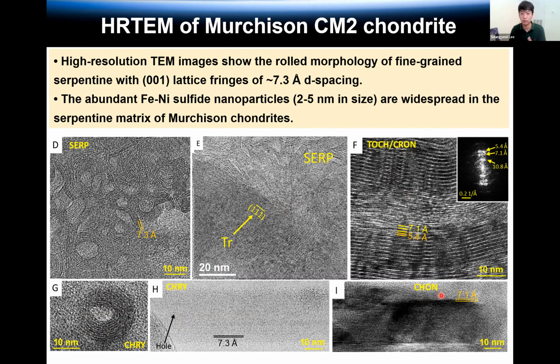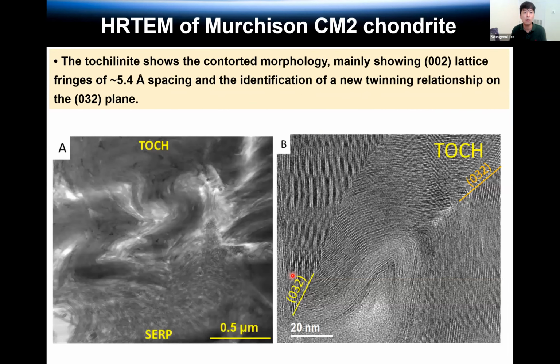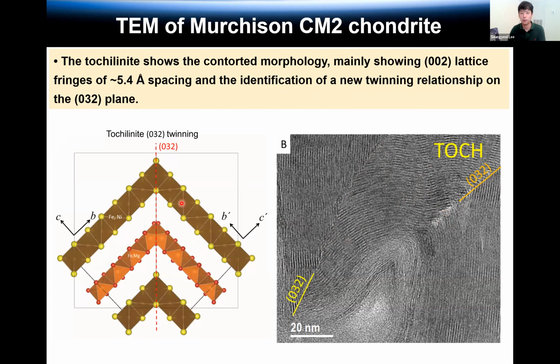So the high resolution image can help to determine the detailed structure of minerals. And this is tochilinite, and this is tochilinite, with very wavy morphology. Look at the high resolution image. Actually, this is tochilinite, and it shows some twinning relationship. So this line relates to the twinning area. Because tochilinite has a layer structure like clay minerals, it can have these kinds of vertical twinning relationships. So we can observe the vertical twinning in the high resolution image. So yeah, this high resolution image is also very powerful to determine the detailed crystal structure of tochilinite.